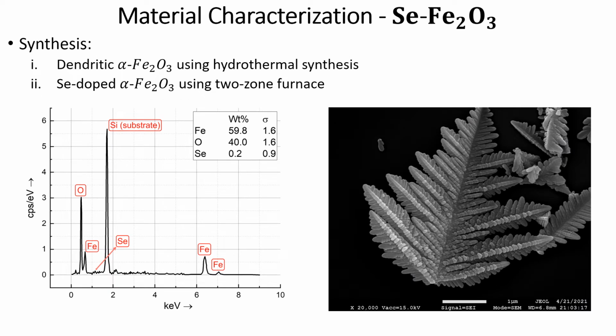The selenium-doped Fe2O3 material used in our device is synthesized using a two-step process. In the first step, we synthesize the dendritic alpha Fe2O3 using hydrothermal synthesis. In the next step, we synthesize the selenium-doped variant of the same using the two-zone furnace.